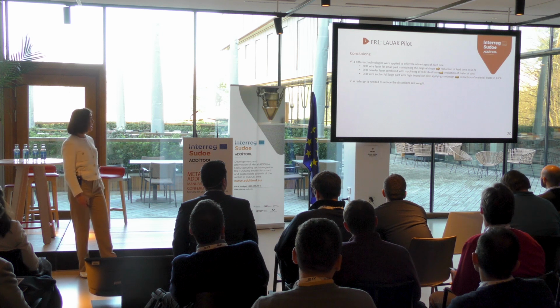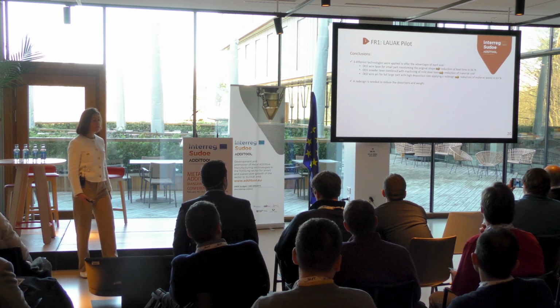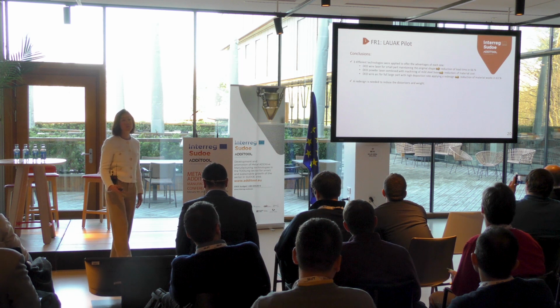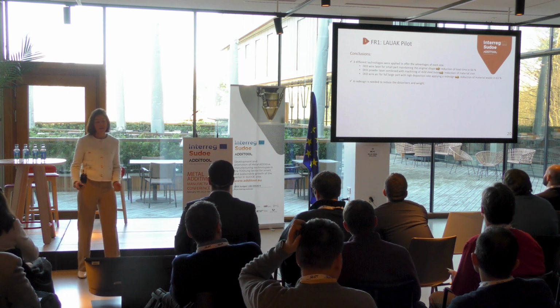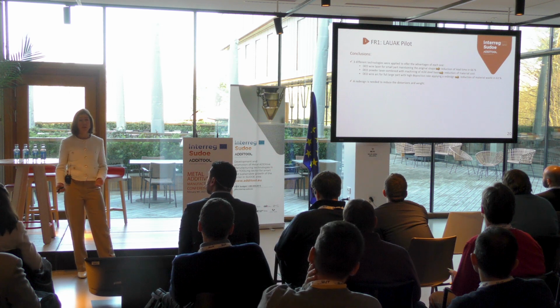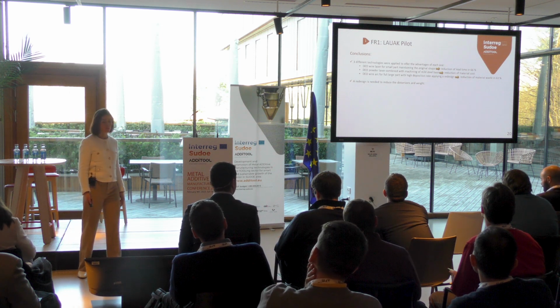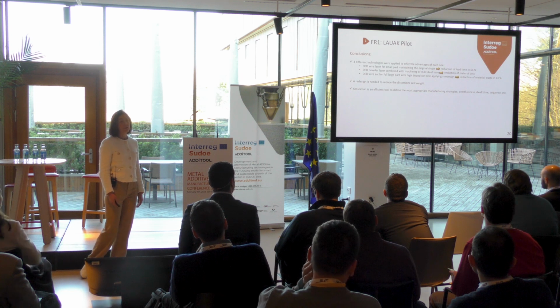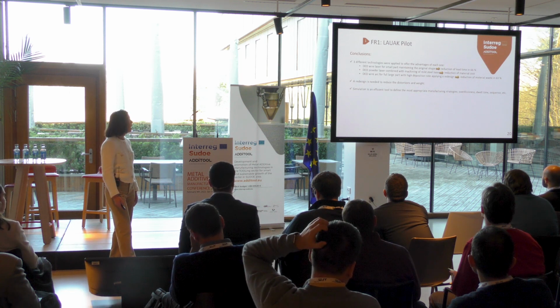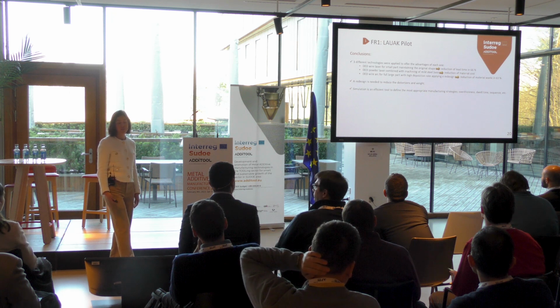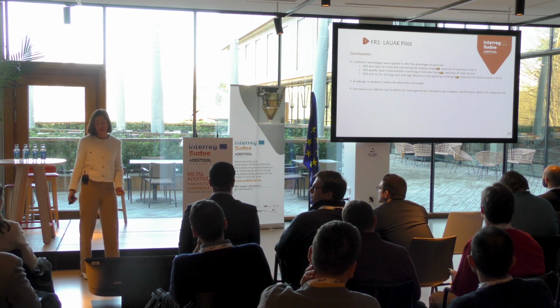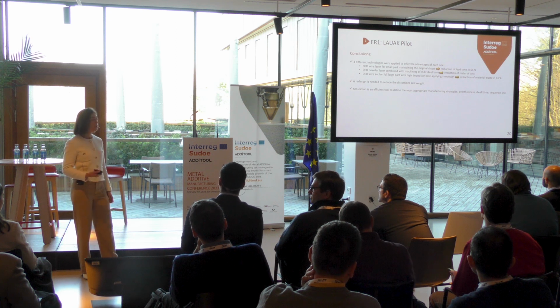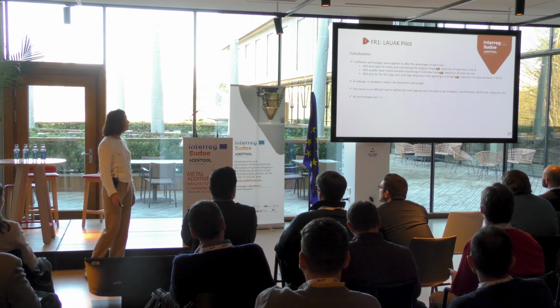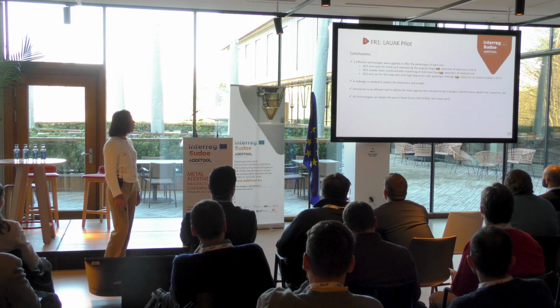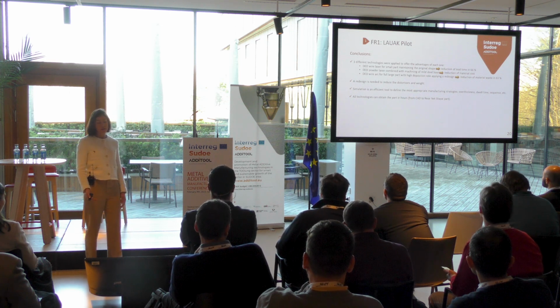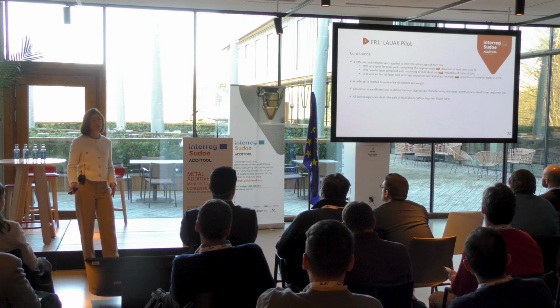In this last technology, a redesign was needed in order to reduce the weight and hence the distortions, because we had to apply less heat input. Simulation demonstrated to be an efficient tool to select the most appropriate manufacturing strategies in terms of over-thickness, dwell time, sequence of robot, etc. All the technologies obtained the part in hours, from the cut to the near net shape part.